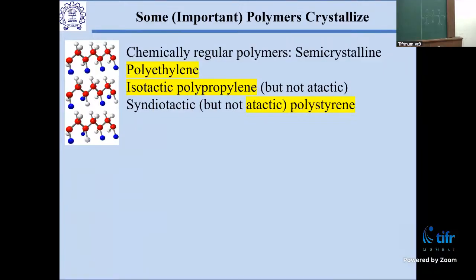The only useful polypropylenes that one makes are what are called isotactic polypropylene. This is the polypropylene that we buy in large quantities, and all the 100 million tons of polypropylene that we're talking about is all made using the catalyst that gives you this. So once you have materials that look like this, then they can actually crystallize to form ordered structures. And so polyethylene, isotactic polypropylene, but not atactic. If I get atactic polypropylene, exact same chemistry, right? It's a CH2, CH3, right? The exact same chemistry, but it cannot crystallize.